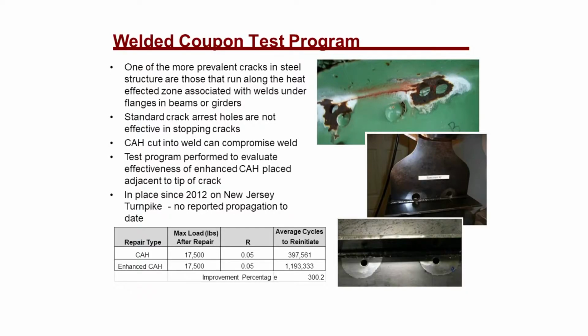We also looked at a welded test coupon because, as you know, most of your cracks come from some feature like a weld seam. So how could we protect or put in a crack arrest hole near a weld seam? Because that residual stress field actually gives you a radius around that hole, all the way around it, you can actually put your treatment adjacent to the weld line and still capture the crack tip in the compressive field, keeping it from growing. So in the tensile test that I just showed you, we got a 13-to-1 improvement. On a weld line, we managed to get a 3-to-1 improvement. So still pretty satisfactory considering the standard alternative.